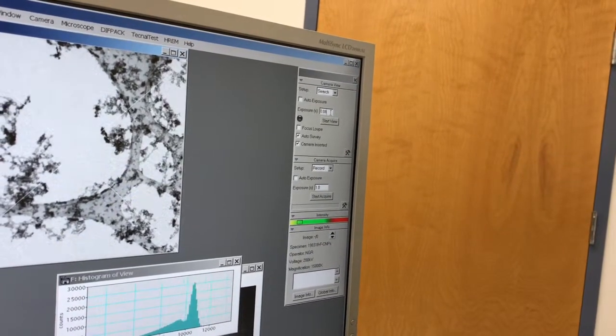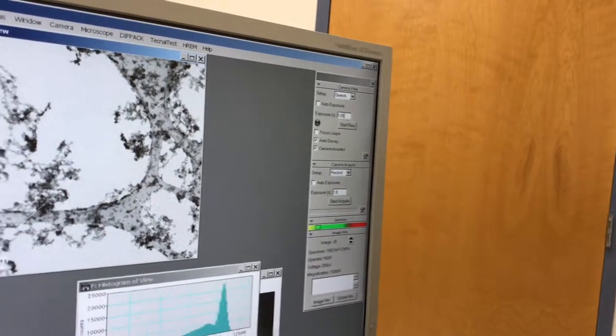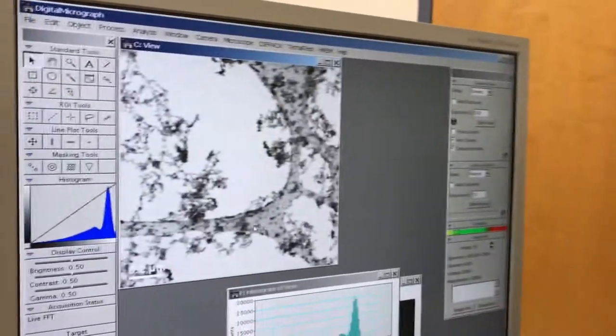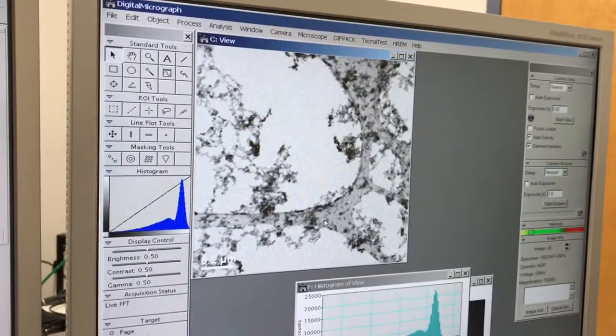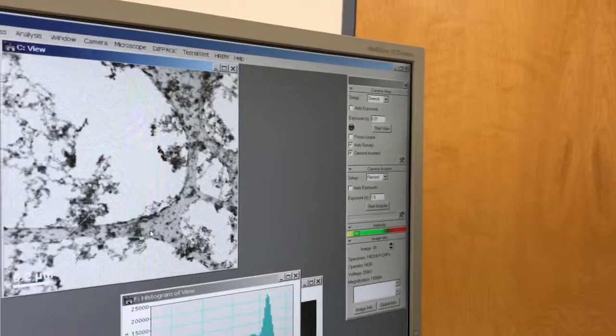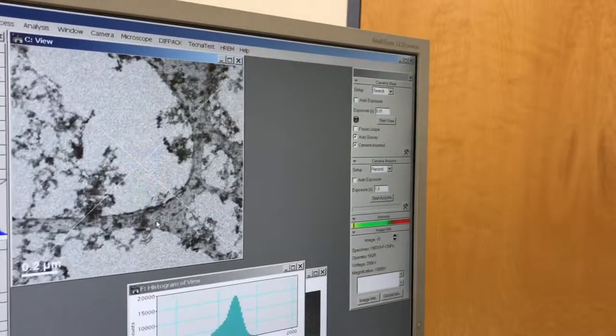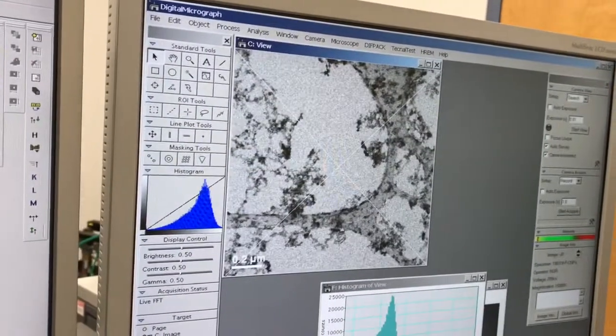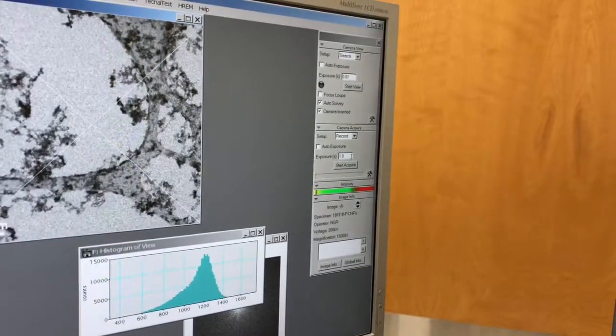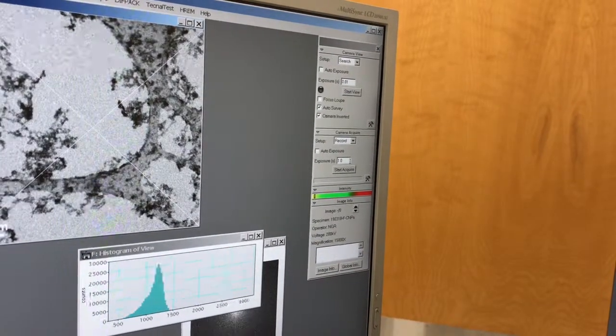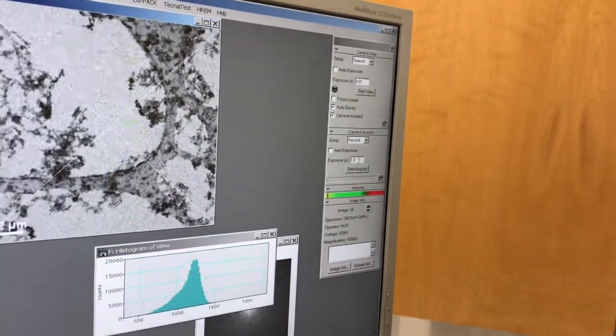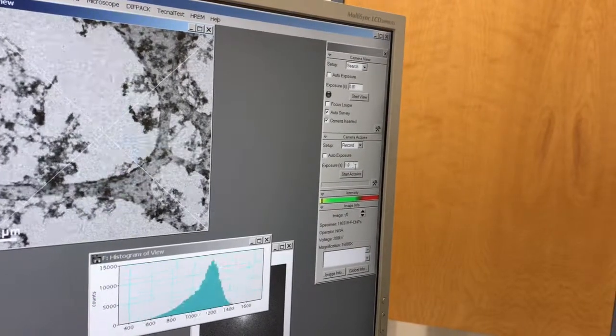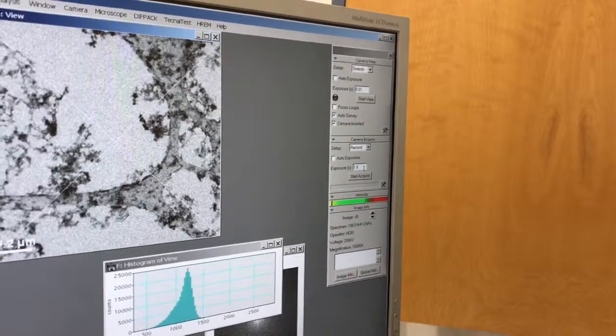So in other words, if I have 0.1, because that's just an easy multiplier here, and I want to get an image with the same signal to noise in my acquired, because the acquired has 16 times the pixels, I've got to use 1.6. If I have 0.02, I've got to use 0.32. Again, theoretically. Generally speaking, I use a multiplier of about 10.